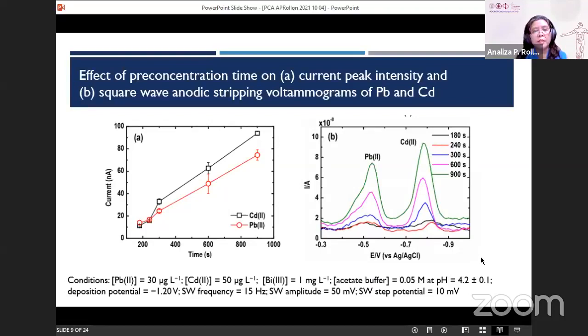So in the first experiment, we can show you here that we have the current versus time. That is the pre-concentration time where the metal is concentrated or deposited into the film on the working electrode. And then we can see here that as the pre-concentration time increases, the current, or the peak height, also increases. And as the pre-concentration time increases, we can see increasing current.